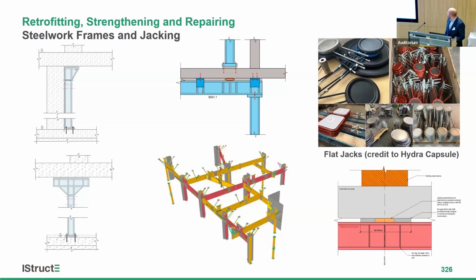It is common to use flat jacks, such as the one shown in the picture by Hydra Capsule. These are like capsules permanently injected, and they're left there as a permanent part of the structure with the load permanently jacked into them. They're quite slim, up to about 50 millimeters, so they can be accommodated in quite a limited structural depth.